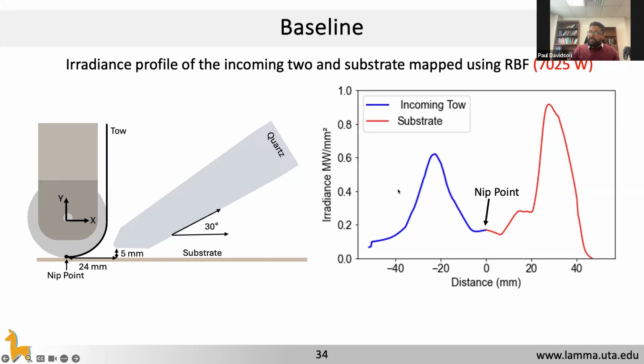With this, you can see that the maximum irradiance which you get is not at the nip point. It is, in fact, quite far away from the nip point, and that is by design. That is because there is a thermal mass as the toe is passing through the flux field. The thermal mass is such that it allows for conduction within the toe to happen and then heat up the material, that is the thermoplastic. And that time, or the distance, is required for that to happen, right? As we know, it is the fibers which heat up and then heat up the matrix itself. But for joining of two surfaces, we need the matrix to melt to be able to join the two surfaces.